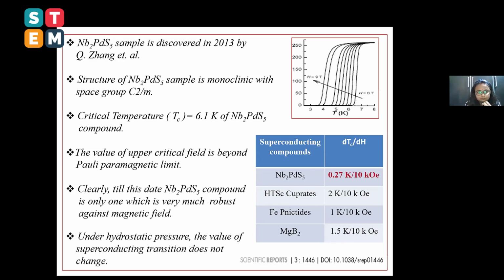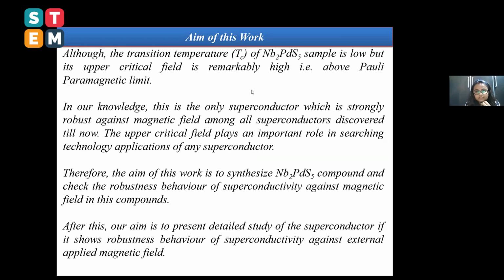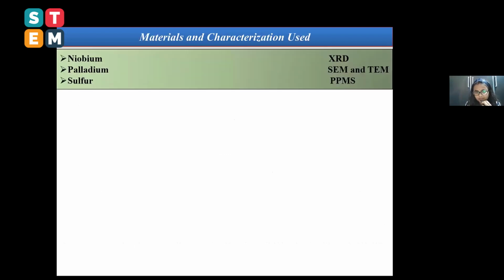Although the transition temperature is low, the upper critical field is very high. To our knowledge, this is the only superconductor which is very robust against magnetic field. Therefore, the aim of our work is to synthesize the Nb2PdS5 sample to check the robustness of superconductivity against magnetic field. After this, our aim is to present a detailed study of this compound if it shows robust behavior of superconductivity against magnetic field. The materials used for this experiment are niobium, palladium, and sulfur, and the characterization techniques used are XRD, SEM, TEM, and PPMS.